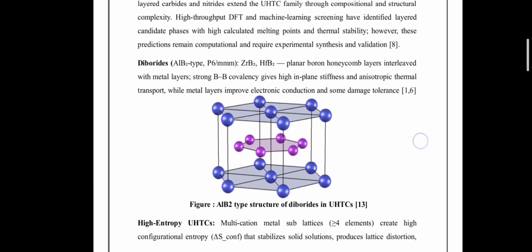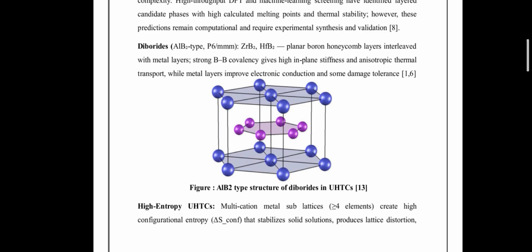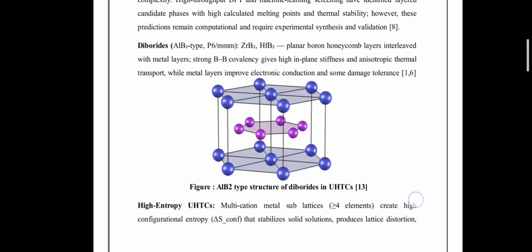The other class is the diborides. The diborides, including zirconium diboride and hafnium diboride, adopt a hexagonal AlB2-type structure consisting of boron-rich honeycomb layers separated by metal planes. Strong boron-boron covalent bonding results in very high in-plane stiffness and anisotropic thermal transport, while the metallic layers enhance the electronic conductivity. The AlB2-type structure of diborides can be clearly seen in that figure.